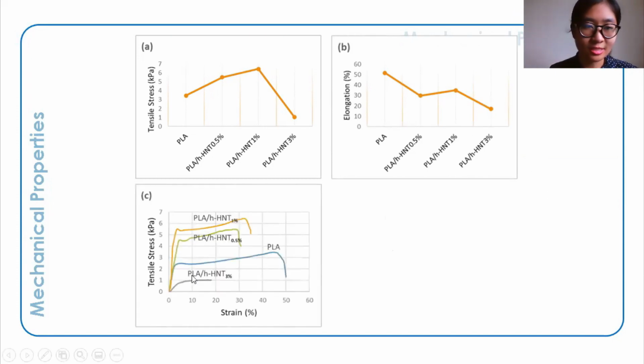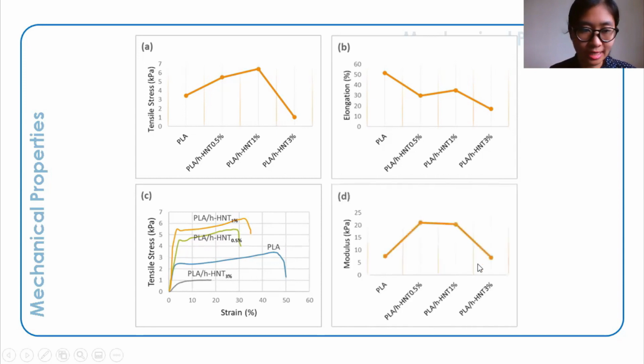The third graph is the stress-strain curve to measure the elastic modulus of the samples. 0.5% and 1% h-HNT content has the highest modulus. At 3% h-HNT content, the electrospun fiber mat has low tensile strength and modulus. This may be due to the formation of clay agglomerates being a source of weak points resulting in reduced mechanical performance, as observed in other papers.